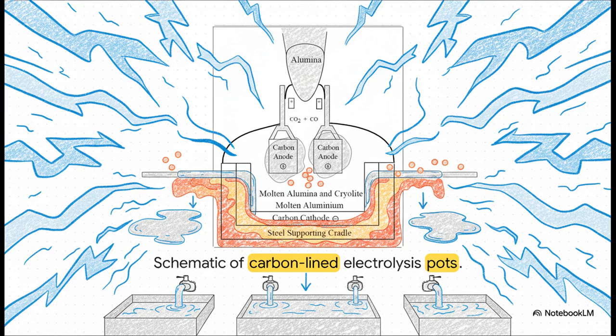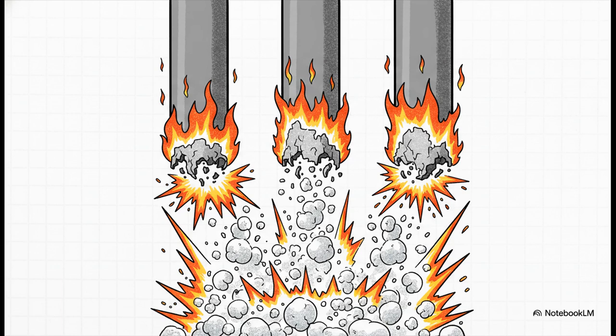And there's a really beautiful bit of physics that happens next. At 1273 Kelvin, the newly freed pure liquid aluminum is actually denser than the molten cryolite floating above it, so it safely sinks right down to the bottom of the pot, resting on the carbon cathode where it can be tapped and collected. But there's a catch, and it's a big one.